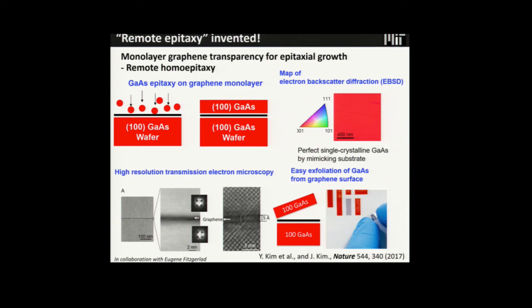So first experiment was as following. We transferred the monolayer graphene on 100 gallium arsenide wafer. Of course, it's expensive. Then we performed the epitaxial growth of gallium arsenide film. Then if graphene is still seed layer, you are not supposed to have a 100 gallium arsenide. You are supposed to have a 111 gallium arsenide. But we get the single crystalline gallium arsenide. Wow. Underlying substrate, really the seed layer.